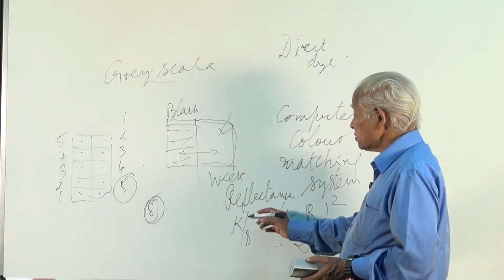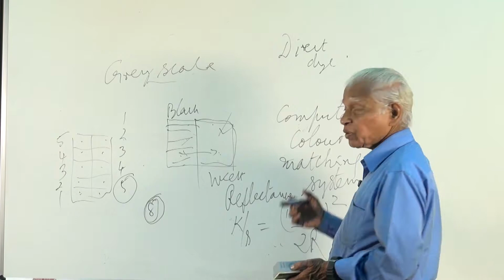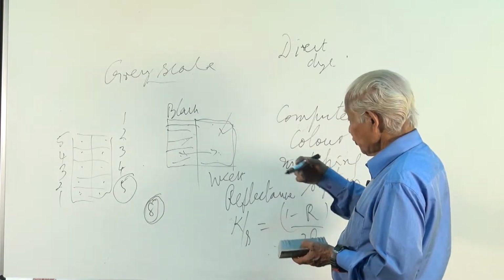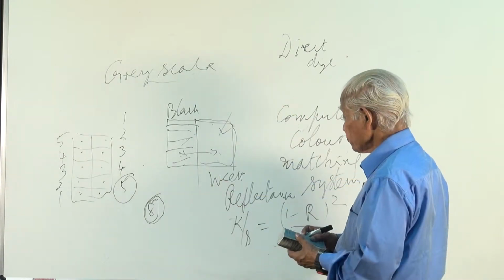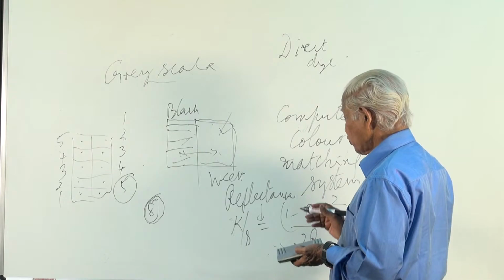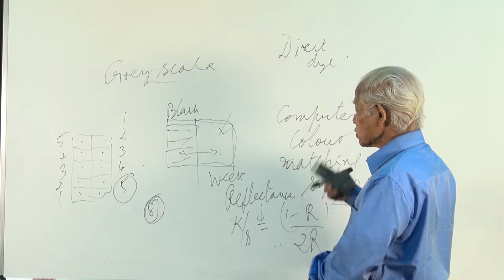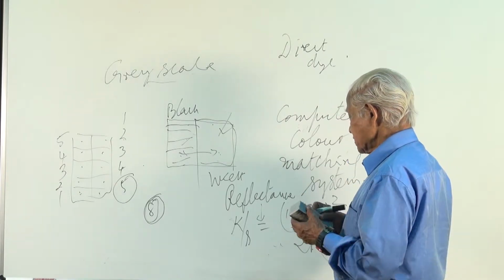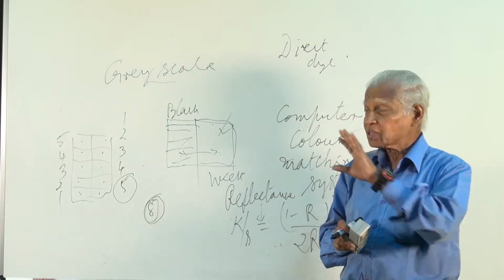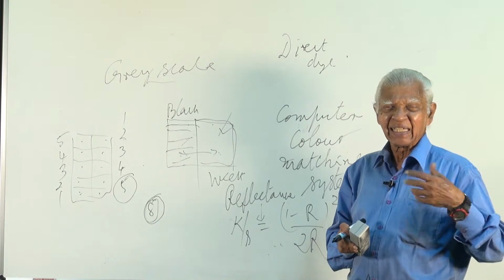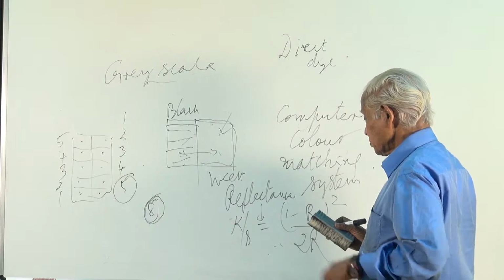And suppose the material is washed and then the K/S value is determined using a computer color matching system. And before washing we have the K/S value and both are identical, it means that the fastness is excellent. Suppose there is a drop in the K/S value following washing, that means that the wash fastness is poor. Or after exposure to the sunlight, the fastness is found to be poor. So this is a better way of checking the fastness compared to using the grayscale, which is somewhat inaccurate, so to say, whereas the computer color matching system is accurate.